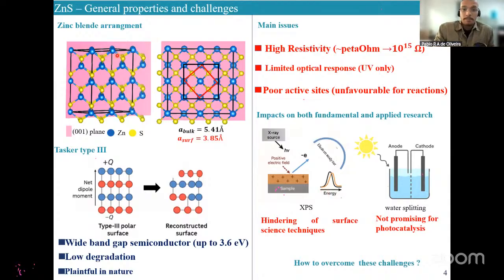Specifically in the right panel, I'm highlighting the bulk lattice parameter of 5.41 angstrom and the surface lattice parameter, which will be of particular interest for us. And this is the top view of the 001 plane. Why the 001 plane? In short, the 001 plane as well as the 111 plane display Tasker type 3 signatures, which means that we have alternating layers of positive and negative atoms, such that a dipole moment perpendicular to the surface results.